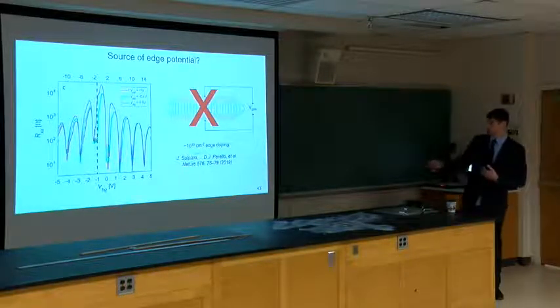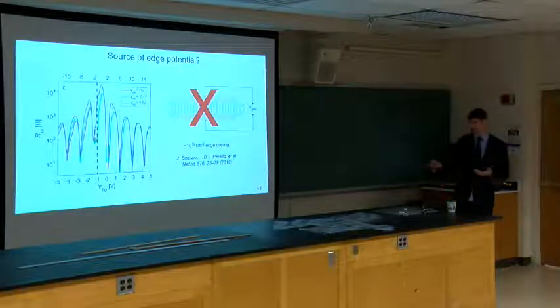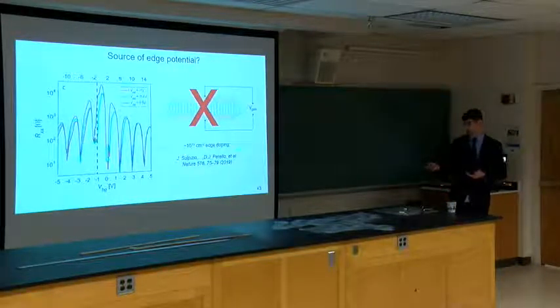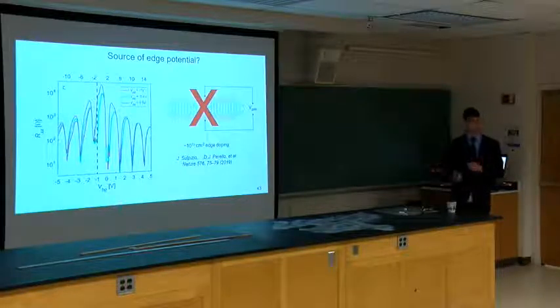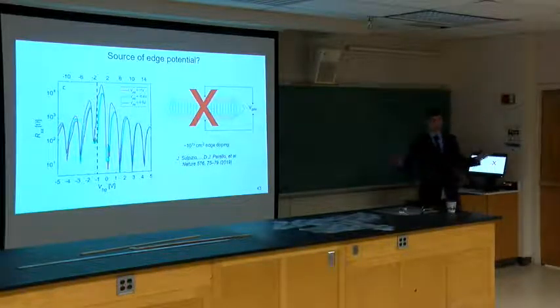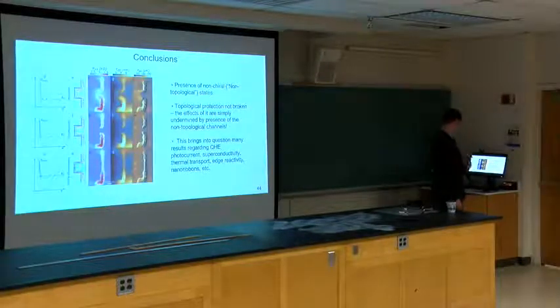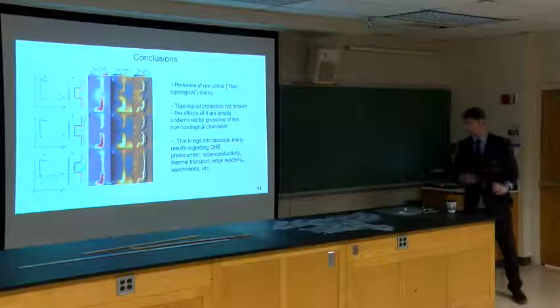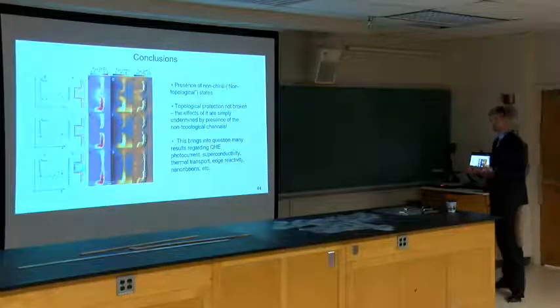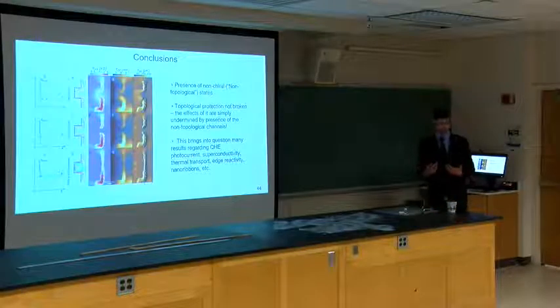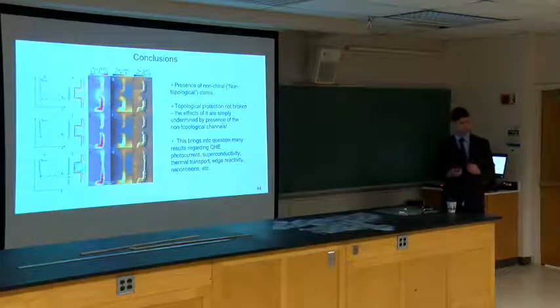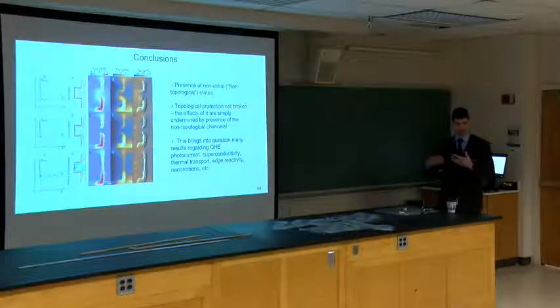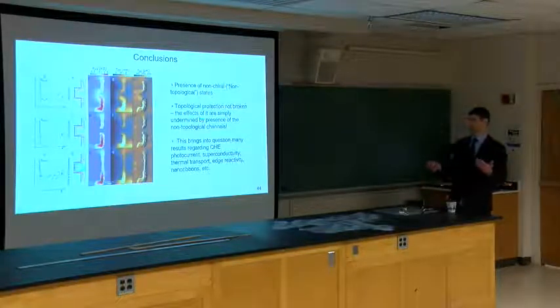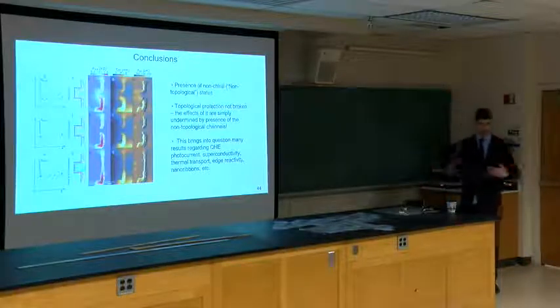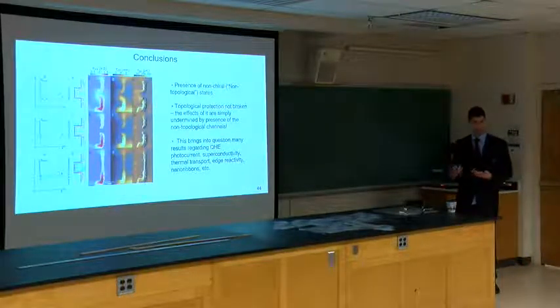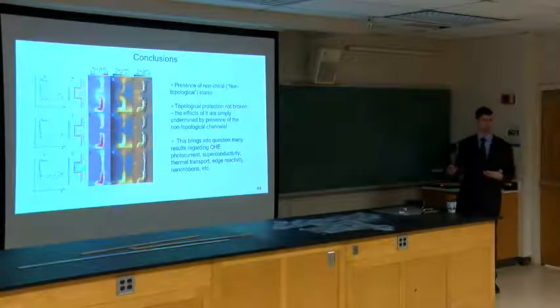So it's interesting. And as it turns out, in another work of mine, a collaboration with a different group, we're able to see a similar 10 to the 10 per centimeter squared edge doping. So it does make sense. It's consistent across samples. So the conclusion is, I didn't go too far over, we have a presence of non-chiral or non-topological states. When I say non-topological, these states still could be ballistic, but they're not protected by the bulk-edge correspondence. So they're not representative of the quantum Hall state. Topological protection is not broken here. We are kind of undermining it in that we can get a resistance state that's not reflective of what the actual quantum Hall state of the system is.